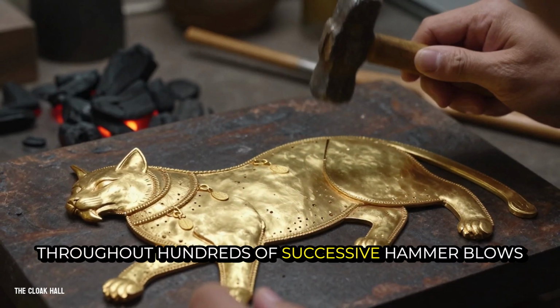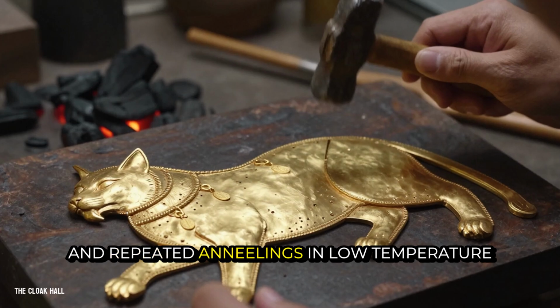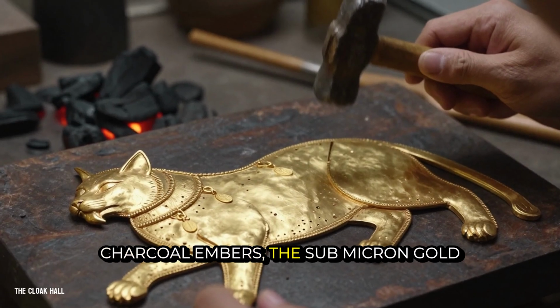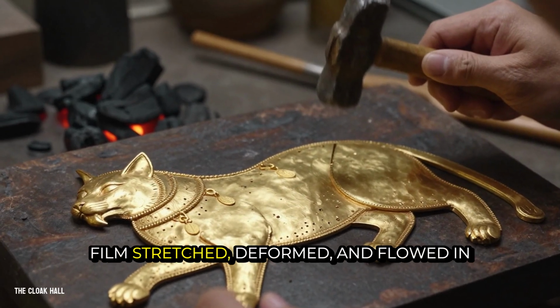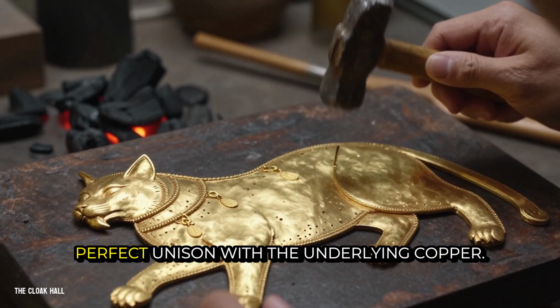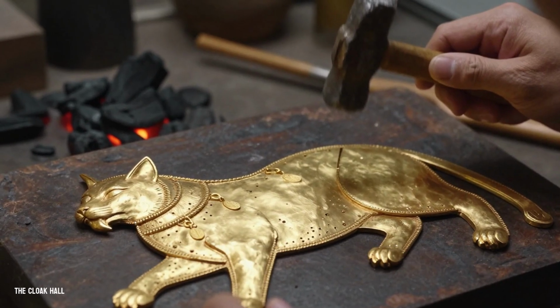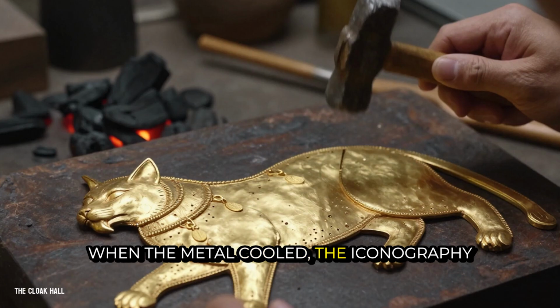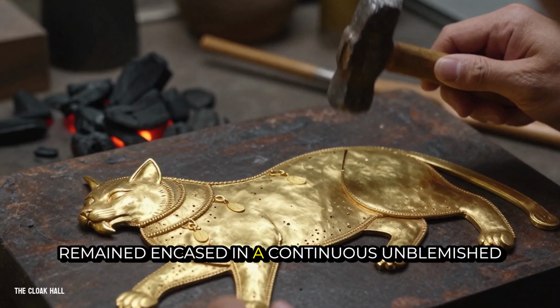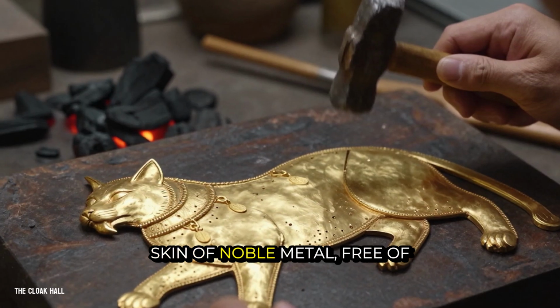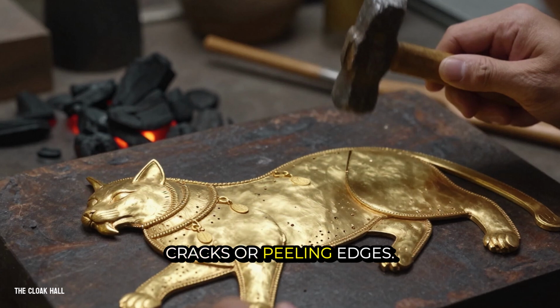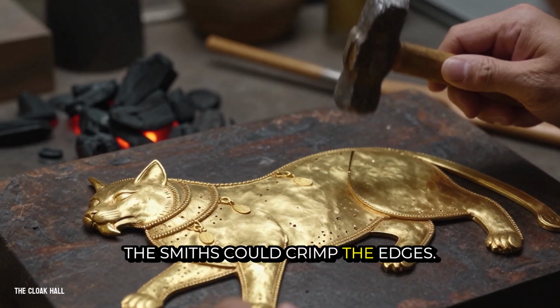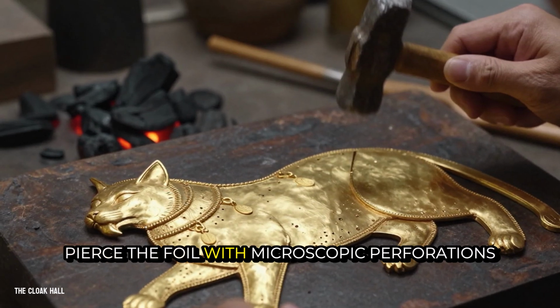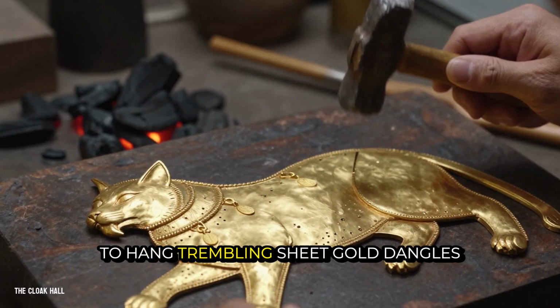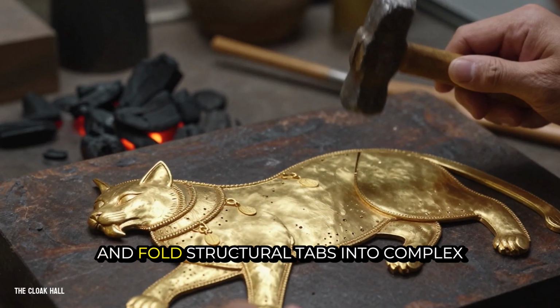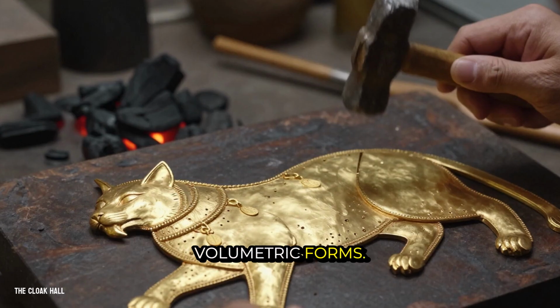Throughout hundreds of successive hammer blows and repeated annealings in low-temperature charcoal embers, the sub-micron gold film stretched, deformed, and flowed in perfect unison with the underlying copper. When the metal cooled, the iconography remained encased in a continuous, unblemished skin of noble metal, free of cracks or peeling edges. The smiths could crimp the edges, pierce the foil with microscopic perforations to hang trembling sheet gold dangles, and fold structural tabs into complex volumetric forms.